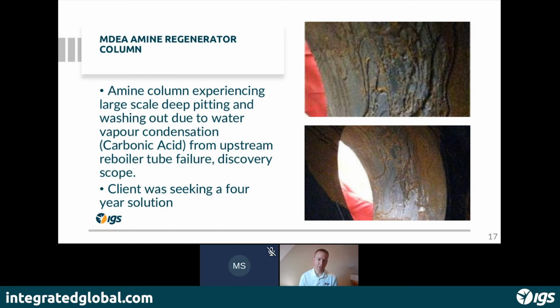With the IGS application, as long as we can see the surface, as long as there's no shadowing of the spray, we can apply the thermal spray system. So if we have deep pitting or deep channeling, as in this case, we'll use a mechanical method like a grinder to open up those channels, open up those pits, being very careful not to remove any more of the substrate material. Once it's opened up, we can then do the surface preparation and apply the thermal spray system.